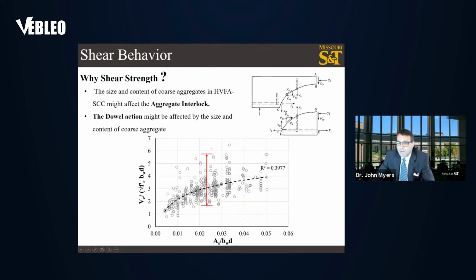In general, shear failure is frequently sudden and brittle, and this figure gives you an idea of how the scatter of the data is. In addition to modifications required in the high volume fly ash SCC mix, designed to produce a flowable, non-segregating, self-consolidating concrete, might raise concerns by engineers and designers regarding the high volume fly ash shear strength.